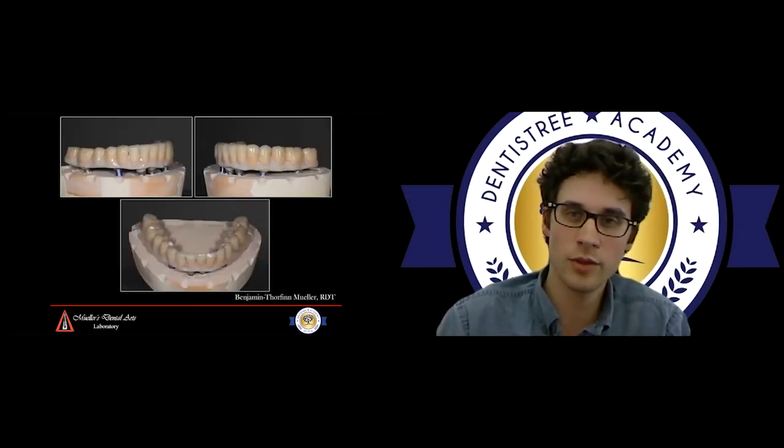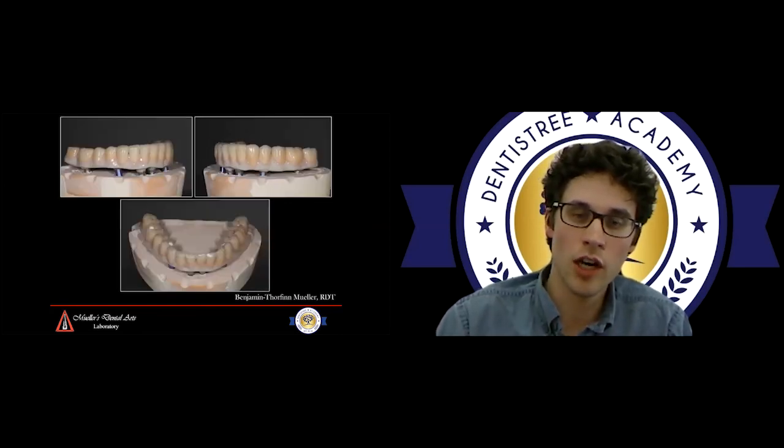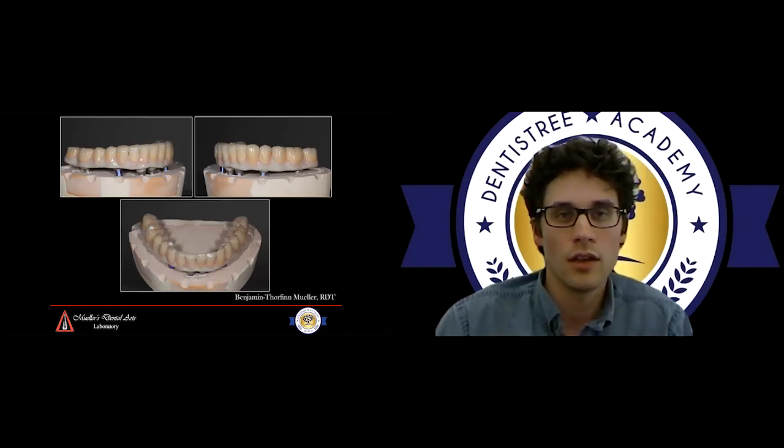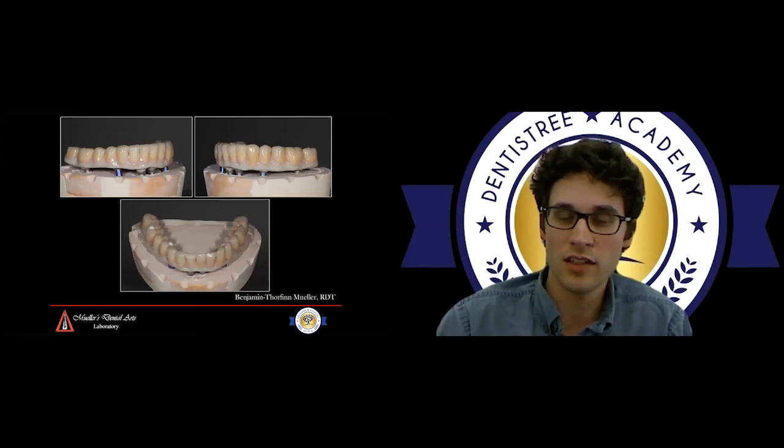You can see the intimate fit of the locator-style attachment systems — this is the Novaloc system. The nice thing with PEKK is you can bond to it. It's extremely biocompatible and you can chemically wet the surface, so you can truly bond to it. These are lithium silicate crowns on top of the PEKK framework, bonded to it — it's not like having a zirconia arch with preps where you're cementing zirconia crowns separately. With true bonding, this becomes one stronger unit. Everything gets finished with pink composite. These are monolithic lithium disilicate crowns — this was a cost decision; the patient did not want to spend the money for layered. But it still looks great, and lithium silicate generally has higher translucency, so things look nicer from a monolithic point of view versus a lot of zirconia options.